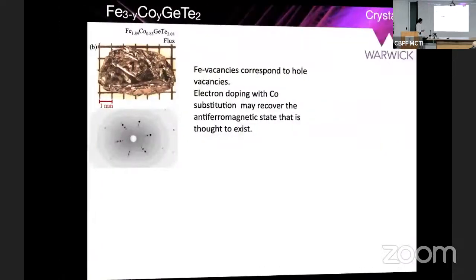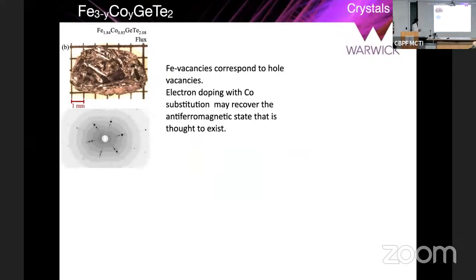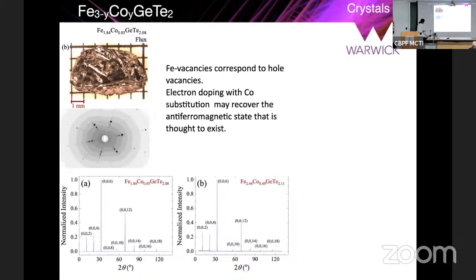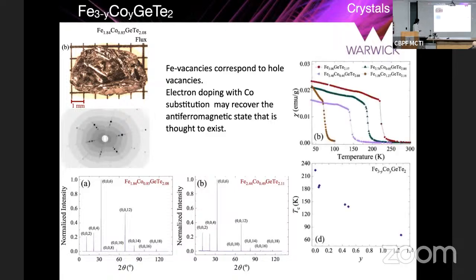One further thing that you could do with this is again play with the lattice, and you can substitute the iron with cobalt because there are a lot of iron vacancies, as I said, and it was previously proposed that you could do this to recover the antiferromagnetic state that was thought to exist before it went ferromagnetic. So here again, we've done a lot of crystal growth to obtain crystals with varying cobalt substitutions in the FGT, and the TC is suppressed as you add cobalt. You can get a lot of very nice crystals with very distinct cobalt substitution and look for this antiferromagnetic ordering, and that's in progress now.